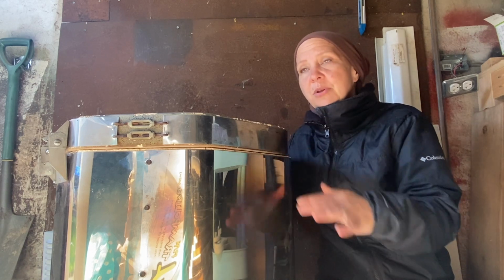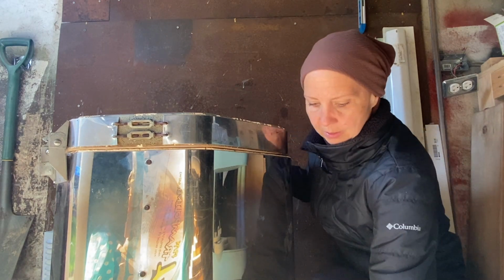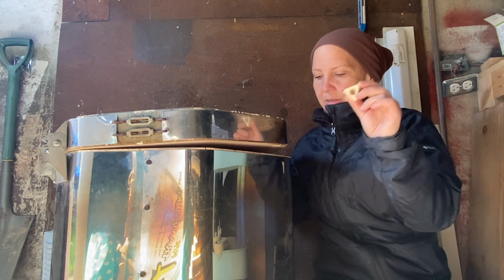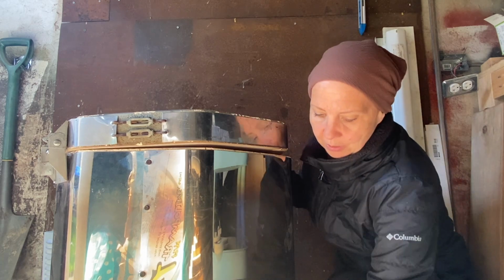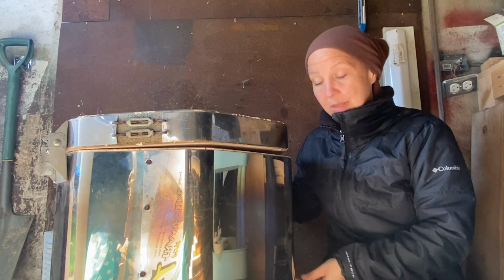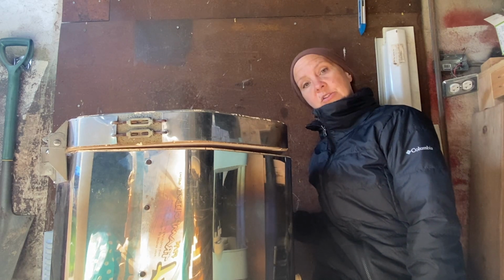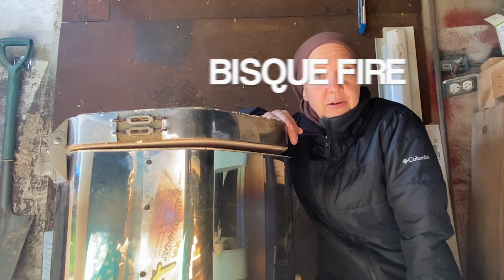You're gonna load up your kiln, have your cones in. You are going to vent the lid. I just have a small riser that I use. You're gonna put 1 peephole in the bottom plug, and you're gonna set your kiln to low, okay? You're gonna let that fire for your bisque ware.